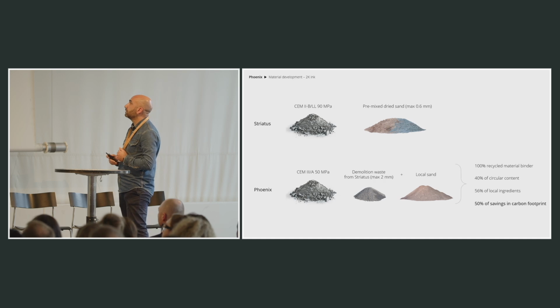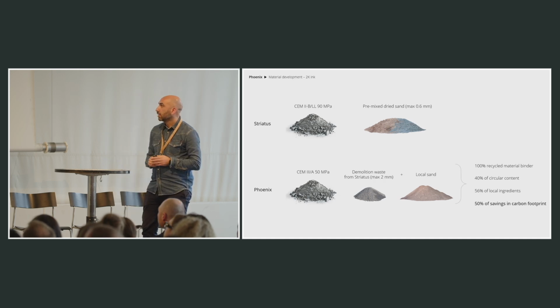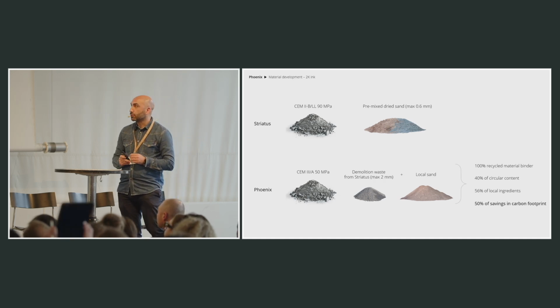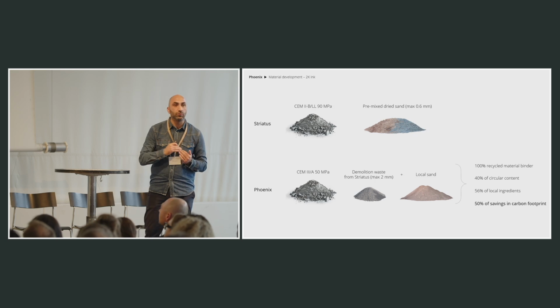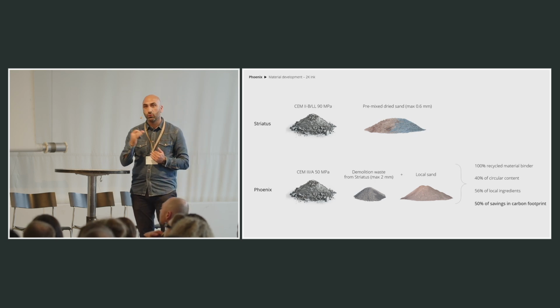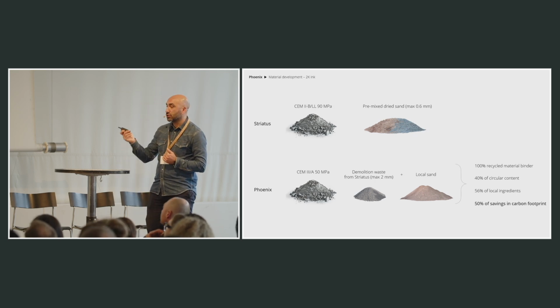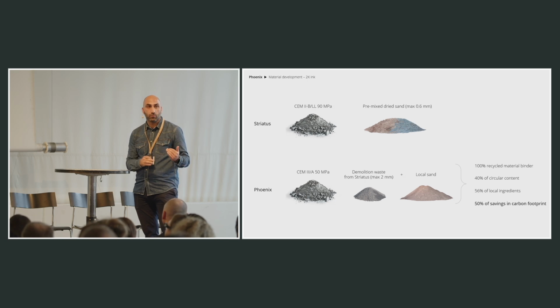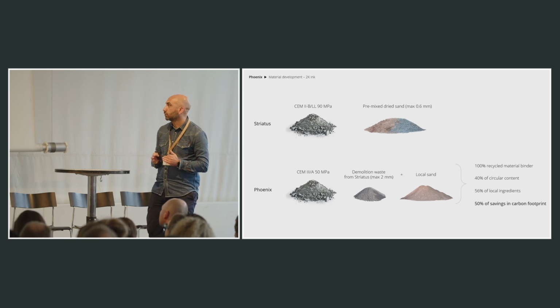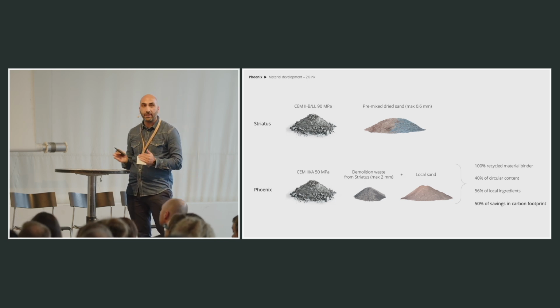Coming from 100% recycled material, we use part of the demolition waste from Striatus. We could increase the aggregates to 2 millimeters, and we actually use local sand. So it was a local sand closer to the plant where we printed the components.